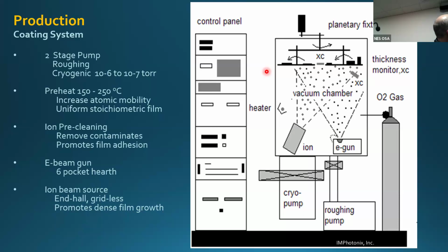Since we're doing physical vapor deposition, the amount of energy that the molecule has when it arrives at the substrate is limited to the energy it's carrying when it gets evaporated. And the further away it is, the less energy it's going to have. So we have to preheat the substrates to increase the energy level so you can get good molecular bonding at the substrate level. We preheat the substrates, depending on the type of substrate, up to 250 degrees centigrade. So it gets very hot. We can augment that with ion beam bombardment from an ion gun using argon ions. That adds more energy to the surface.